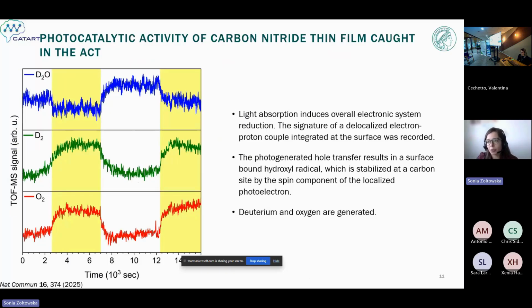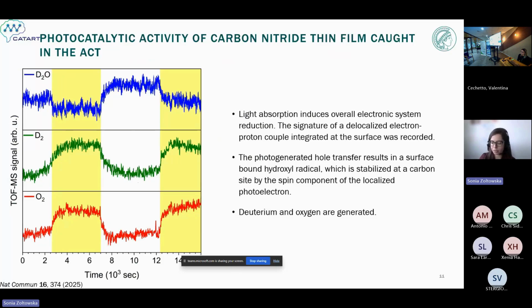So in general, we can say that light absorption induced overall electronic system reduction, and it shows us the signature of the delocalized electron-proton couple, which is integrated at the surface. And the photogenerated hole transfer results in the formation of a surface-bound hydroxyl radical, which is stabilized at the carbon site by the spin component of the localized photoelectron.